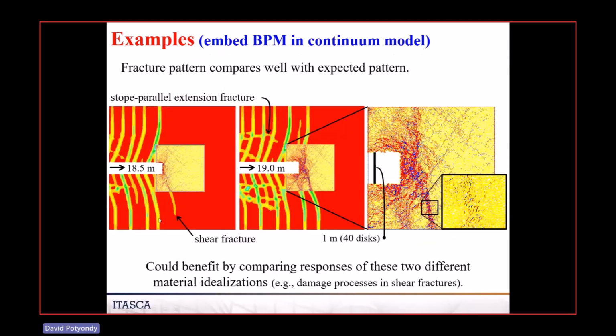And this is just again showing here's the PFC region, there's the broken bonds, and here's the system in equilibrium when the stope is 18.5 meters long, then we carve out some more. And as we do, we start seeing the formation of a new shear band. So this is a strain softening constitutive model that's in the continuum code. And this is just pointing out where the coupling is making sense. We're getting a nice clean thing where the shear band is going from one representation into another. And this shear band in here, of course, you could use to study in detail what's going on in a shear band.